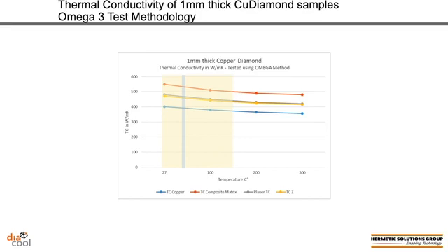The next two bars that you see moving up the chart represent the thermal conductivity of the whole structure, being that copper diamond matrix with the sandwich of pure copper on both sides. In this case, there are two bars, one designating thermal conductivity in the Z direction and the other in the planar or X and Y directions. And you can see the material has high thermal conductivity, in that 490 watt per meter K down to 425 watt per meter K that we actually saw in some earlier slides.